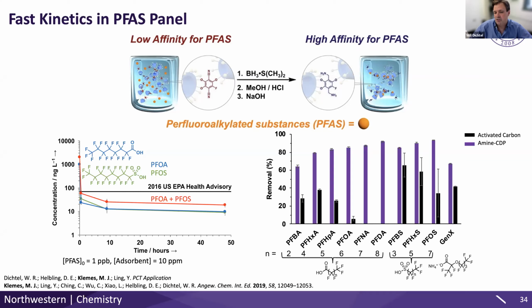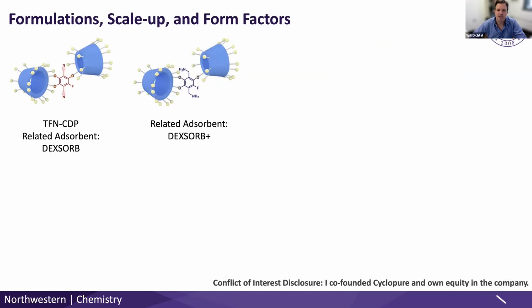Those are even more difficult to remove when they have these smaller chains, and many of these smaller PFAS have now been used to replace these larger ones as the larger ones fell out of favor. Which is something I could editorialize about for an entire hour, but will not here. But in any case, the broad spectrum PFAS removal was great to see. The black bars are removal by activated carbon under comparable conditions, and so this material outperformed activated carbon in several respects.